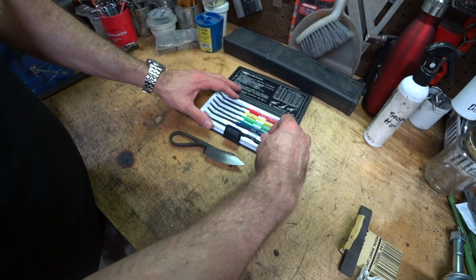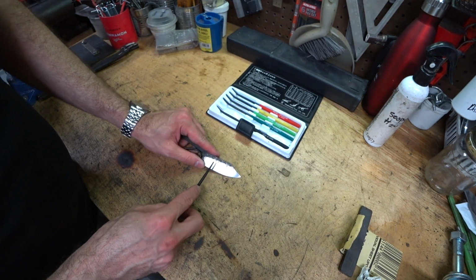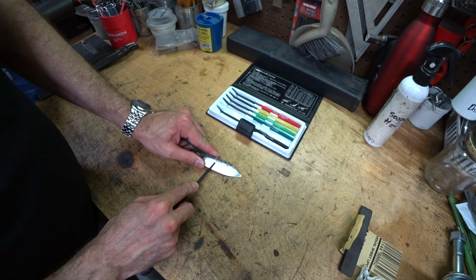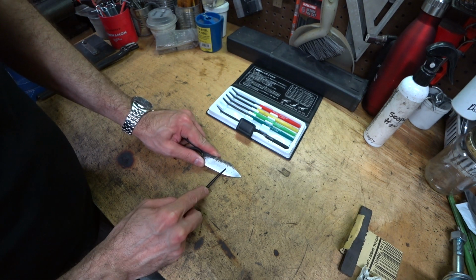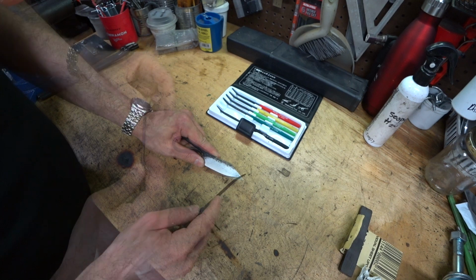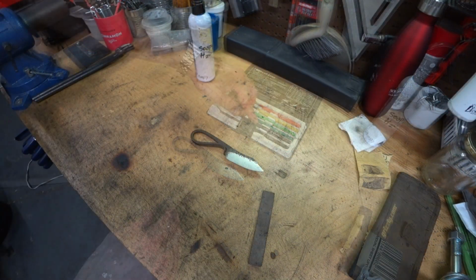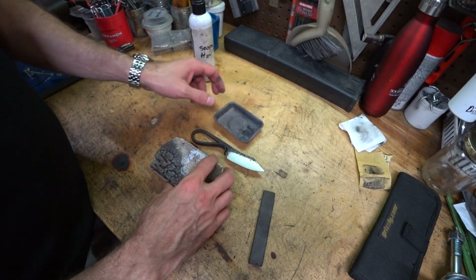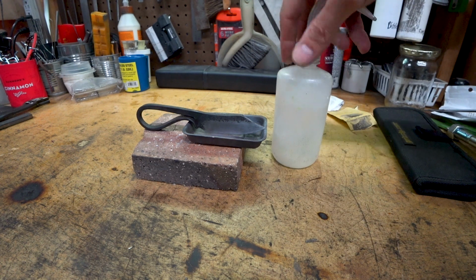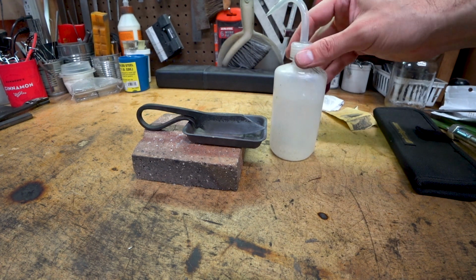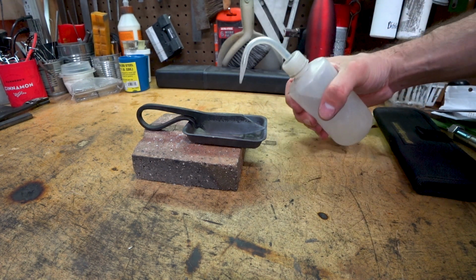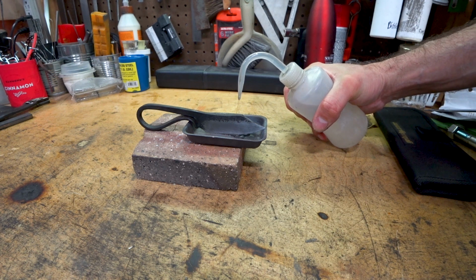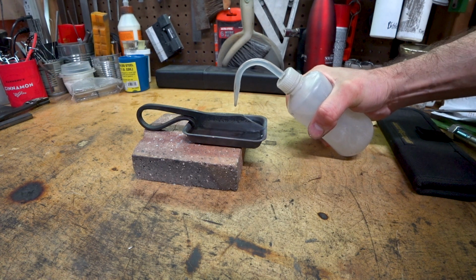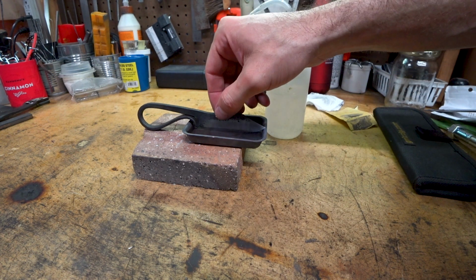We're going to try the 60, and this one just scratches a little bit close to the base of the blade and hardly at all in the rest of the blade. So it looks like this is just under 60 Rockwell. So this step here is going to be completely unnecessary. I'd have a totally serviceable blade if I left it as is, but I'm going to go ahead and take the time to do a selective temper.